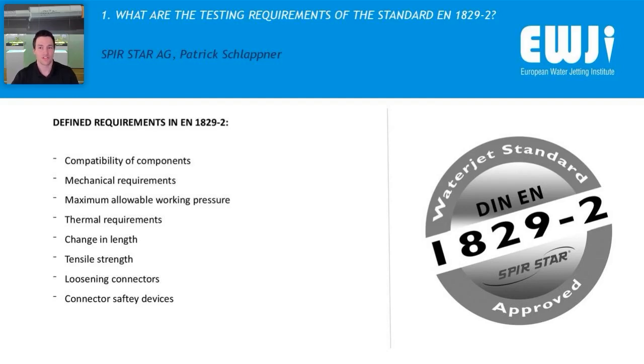Also, thermal requirements are defined in this standard. They say hoses or hose lines should have an operating temperature between -10 degrees Celsius up to 70 degrees Celsius. Additionally, we have the change in length. Any change in length shall not exceed ±2% of the original length. According to the tensile strength, hose lines shall withstand a tensile force equivalent to that indicated by a pressure equal to 1.5 times the maximum allowable working pressure, or 2000 Newton, whichever is the lower value. Additionally, there are some requirements according to losing connectors and connector safety devices.